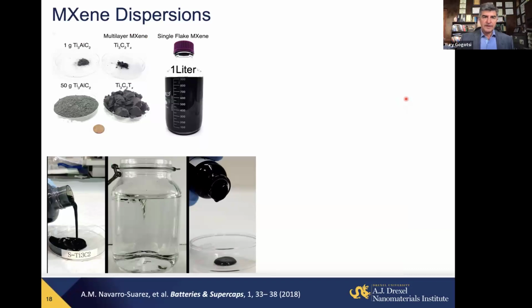So what we do typically in our process, we take ceramic material like titanium aluminum carbide ceramic, we put it in solution, etch it, make something we call multilayer MXene or MXene clay, because after aqueous etching, it's very easy after that to disperse it in water. And we get solution of flakes like a paint that you can spray coat on the walls of buildings.